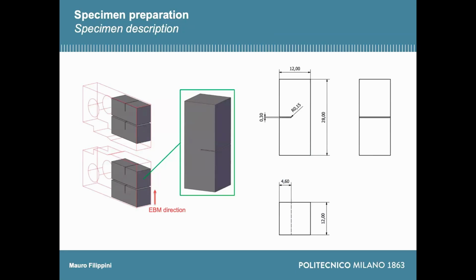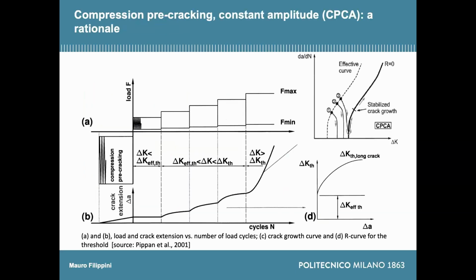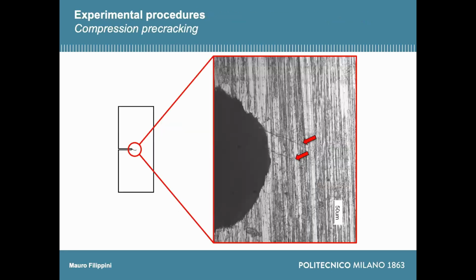So out of specimens left over from a previous activity, we produced this small specimen that we pre-crack. So we generate a notch by wire EDM, and then we produce a crack ahead of this notch by compression pre-cracking. You cannot generate a stable crack in titanium aluminides without compression pre-cracking. You go back to the work of Subra Suresh in the late 80s, beginning of the 90s. And there has been major work by the group of Reinhard Pippan in Austria, in Leoben, demonstrating that using compression pre-cracking, you can generate stable crack growth propagation in titanium aluminides.